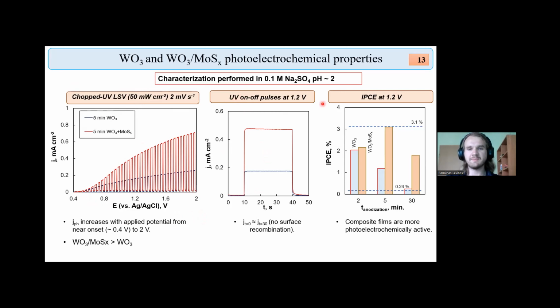The UV on-off pulses at a chosen potentiostatic condition, in this case 1.2 volts, were also performed. And these experiments should show whether the material has surface recombination. If there were surface recombination, the initial photocurrent would have a jump, which would then settle at a constant value after some time. There is no initial jump in this case, which means that there is little to no surface recombination.